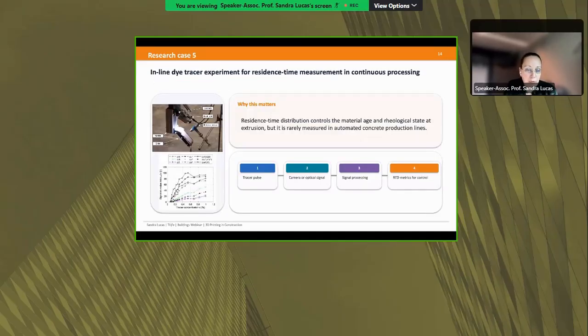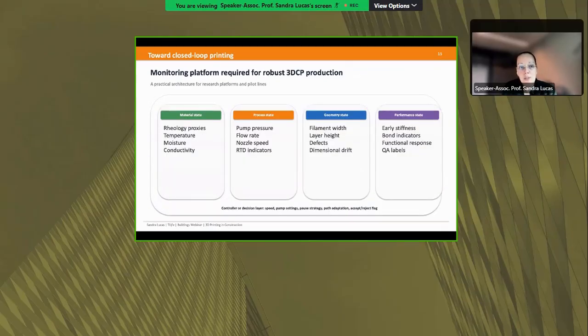So again, another PhD student from my group is working on inline control. So we started with using a dye to trace the residence time in the material. And the goal was also to be able to print in one go, but at the same time to change material while we print. Because the purpose of 3D printing is to make construction faster, safer, and more efficient. And we believe that we should also be able to change material while we print. In order to do that, you need to understand when your new material will show up in the printed part, but we need to trace it back to the mixing system. So we started by developing these inline controls, and from that work, we took some steps further to study and control other parts of the system.